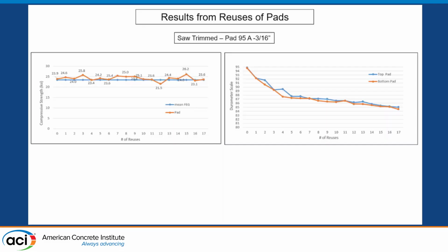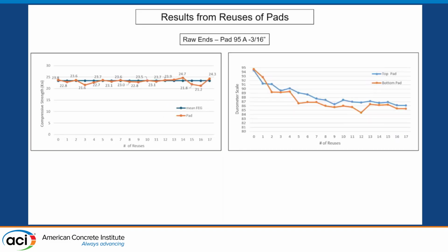And so we thought, okay, if people wanted to use these pads in practice, maybe the 95A 3/16 could be a good solution for full later age specimens to be tested. And as the pad gets softer, it could be used for very early age specimens. And so here's the distribution for the raw ends with the 95A 3/16 pad. Of course, you can see more variability just due to the end conditions of the cylinder.